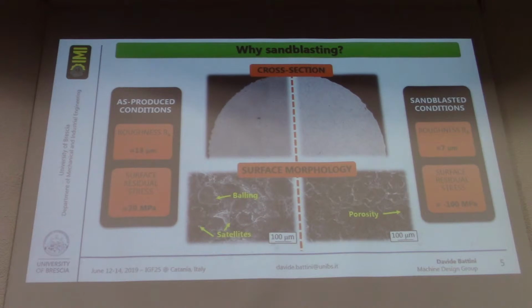On the right we have the sandblasted condition, on the left we have the as-produced condition. The surface looks a lot more uniform, and we also get some surface residual stresses that are positive for fatigue resistance, since we get from plus 70 megapascal to minus 100 megapascal on the surface.